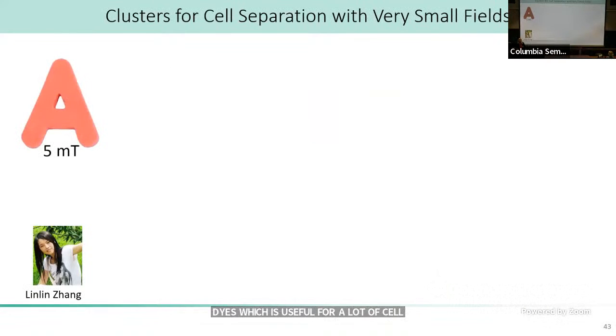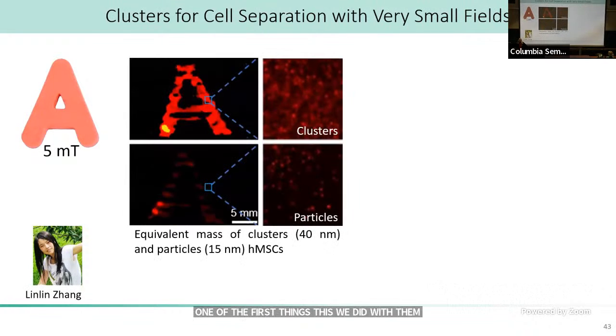One of the first things that we did with them, this is work by Linlin Zhang at Rice University, who works with Gang Bao, one of my primary collaborators. They're very interested in separating mesenchymal stem cells from media. In this experiment they showed that you could tag and target these materials to MSCs. What you're looking at is one of the letters of a toy. If anybody's ever put magnet letters on their whiteboards or refrigerators, they're very, very poor magnets. So we put the letter A underneath, and we were able to collect the clusters very efficiently in a matter of seconds.